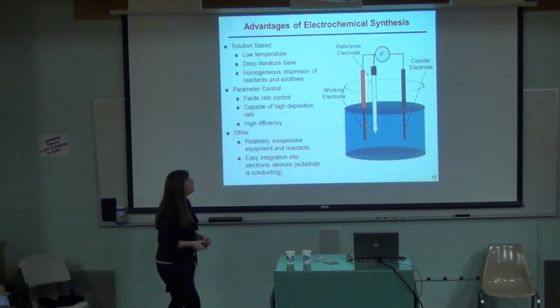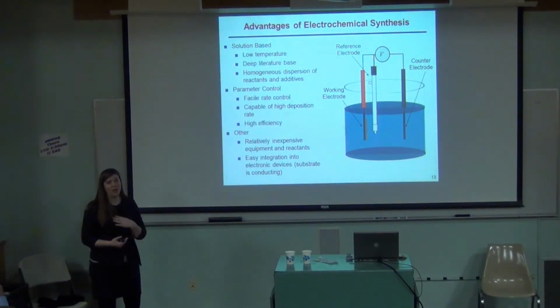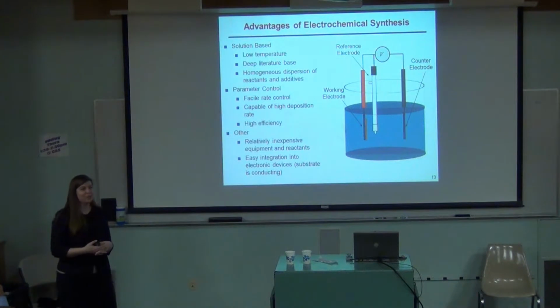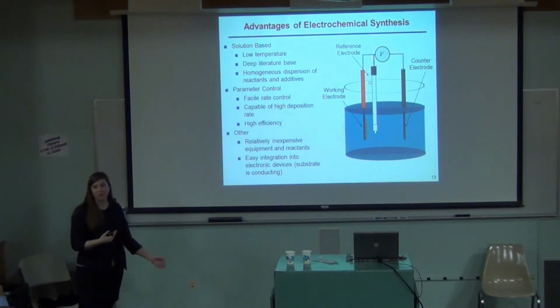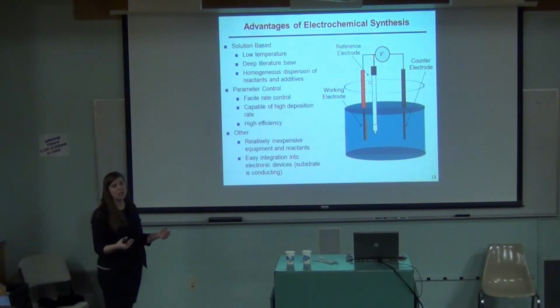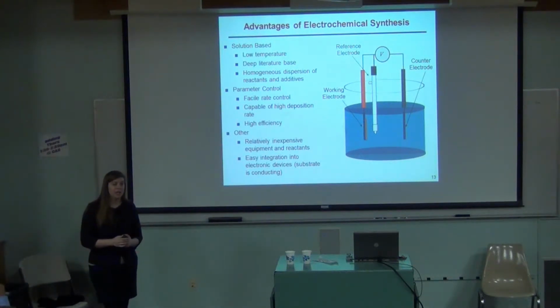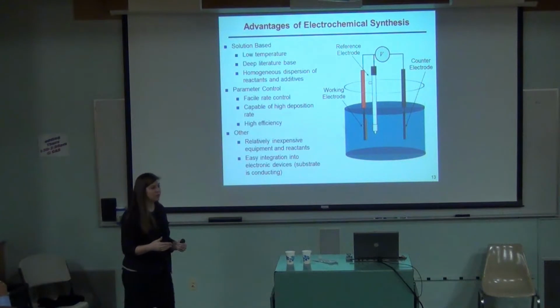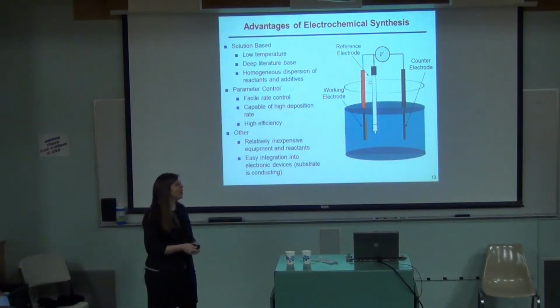So why do we use electrodeposition in my lab? Well, one, it's how I learned how to do these synthesis mechanisms that I have studied for 5 years, so that I just teach that to other people, but there's many other reasons than that. There's a huge literature base. There's also, it's very low temperature, so a lot of synthesis of inorganic materials involve really high temperature synthesis. They put it in a tube furnace, or a box furnace, and they have to heat it up to 1600 Kelvin, really hot. It's not something that could be scalable. If you're going to have to use a lot of energy to make something, then that kind of defeats the purpose of making something green if you have to use a lot of energy to actually make that green material. So you have to think about cost analysis for that.